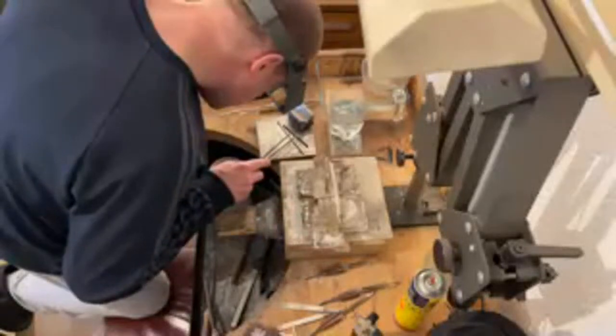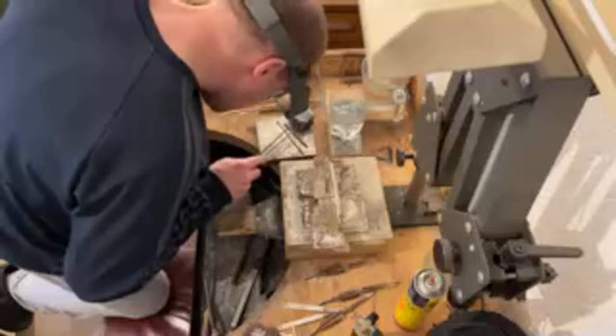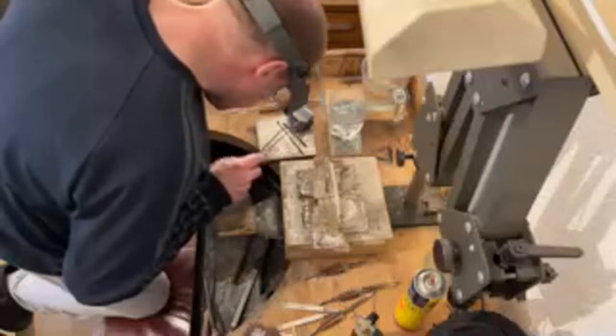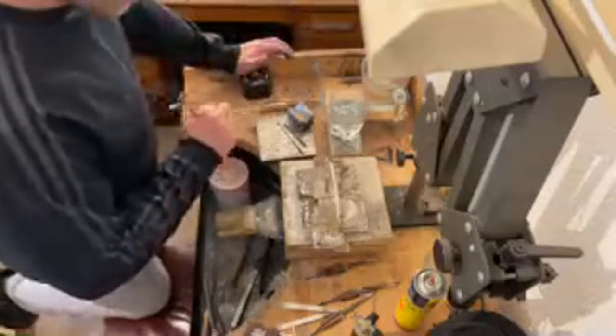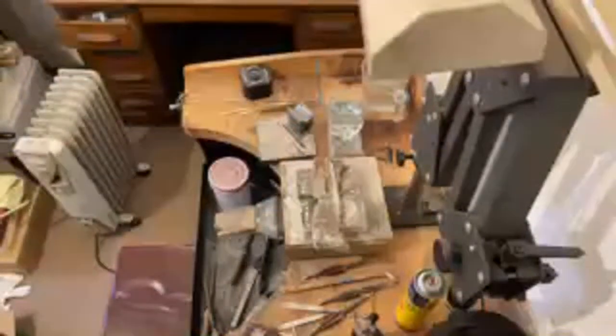Doing it this way, the gold builds up quite a lot of oxide. And that might be why the surface of that gold looks quite orange peely, because when I'm rolling it, I'm not cleaning off the oxide first. And I think that black gold oxide is basically imprinting the gold when I'm rolling it. But still a work in progress. Right, I'm going to anneal those next, and I'll keep you updated on dry quenching. Toodles.